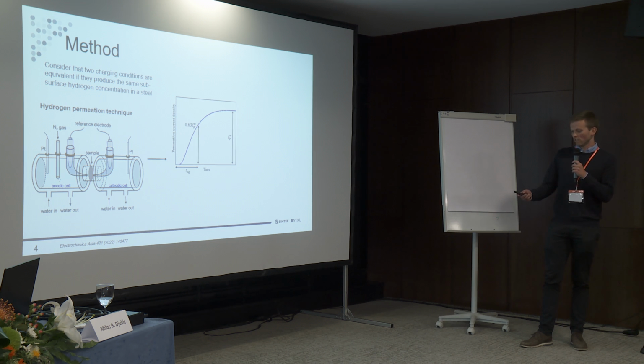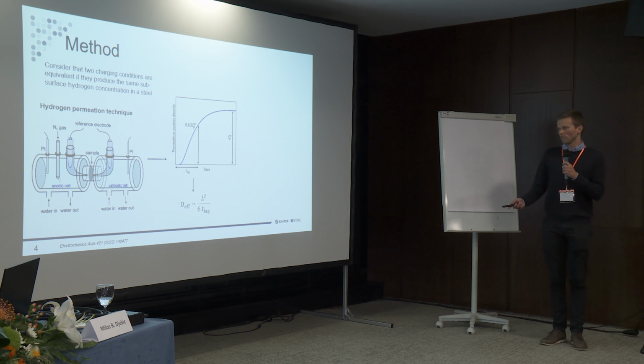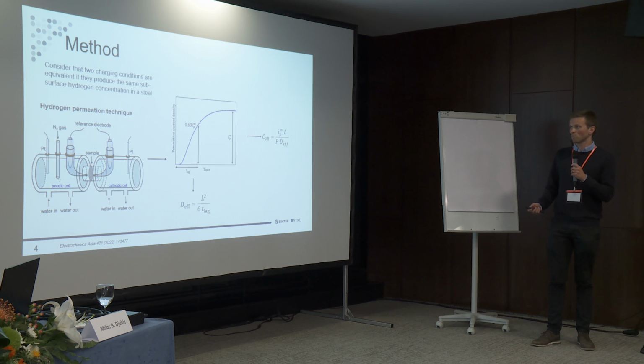For example, by this time lag method, which is based on the time it takes to reach 63% of the permeation current density at steady state. And you can use this equation. We call it effective as traps can affect the transportation of hydrogen through your sample. And then we can use this effective diffusivity together with the steady state permeation current density to calculate the subsurface hydrogen concentration, in this case in lattice and reversible trap sites.